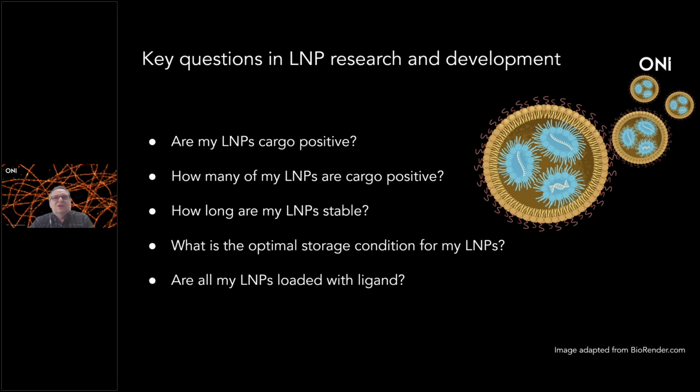The second thing, and one of the biggest problems nowadays in the lipid nanoparticle field, is their stability. How stable are these lipid nanoparticles? If you go back about 3 years to the COVID pandemic, you may remember the vaccines were delivered on dry ice, a very cold environment. They were then defrosted and needed to be used the same day, otherwise they were discarded. That tells you there are still big questions about how stable this particle can be, and that is directly linked to storage conditions.